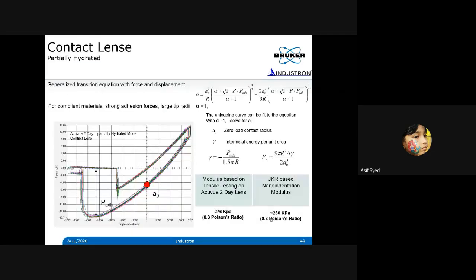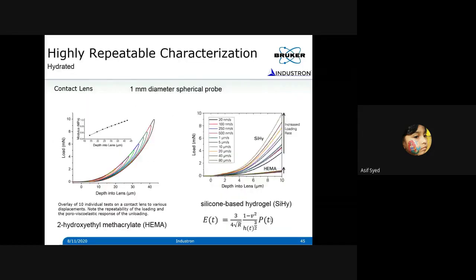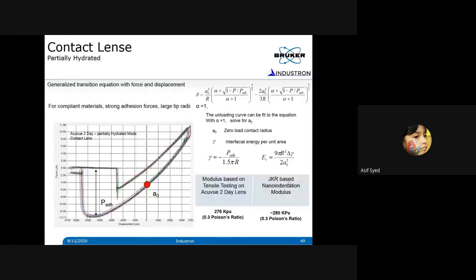Okay. Now, when you do it in a partially hydrated state, like I mentioned, you don't get this nice load-displacement curve the way that you wanted to get, right? When you do a partially hydrated or a dry condition, you will see this kind of load-displacement curve. This is the curve that I started with in the beginning. When you have soft materials, and you have this kind of curve where the tip jumps into contact and then load and unload, you cannot use those adhesion contact mechanics anymore. You need to use this modified JKR method that I mentioned, and you can fit the unloading curve and extract the modulus of the material as well as the surface energy of the sample. You can do both of that.